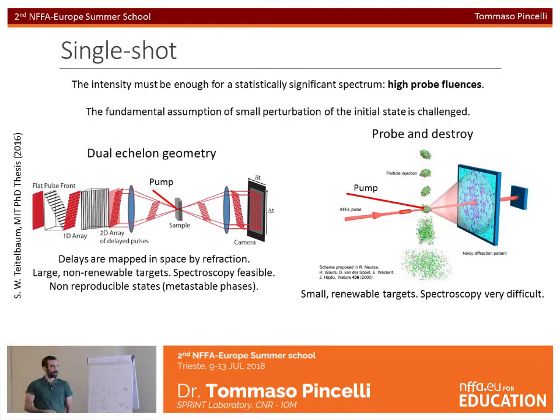The stroboscopic method, as I described it, the pump-probe method, again, probes only the reproducible paths through the phase space of a system. But what if we send a system into a metastable phase by optical excitation? Or what if we want to look at all possible paths that the system takes? Well, then we have to use single-shot approaches. But in this condition, we need the intensity of the probe pulse to be enough to have a statistically significant measurement of the spectrum with a single shot. And therefore we need high probe fluences. So we challenge the fundamental assumption of a small perturbation of the initial state.